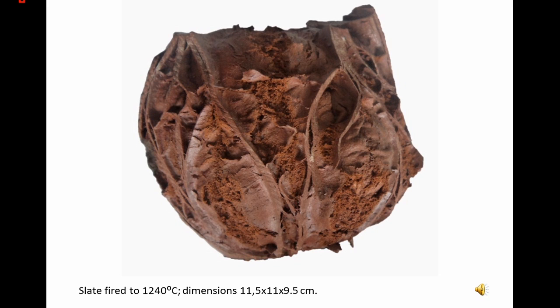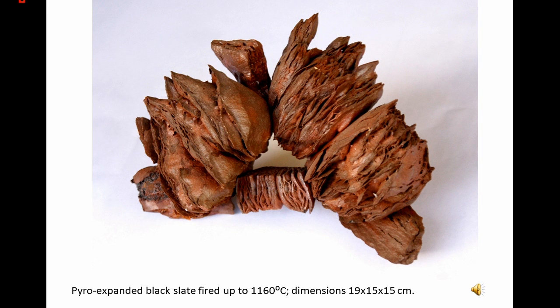Constrained pyroplastic expansion of slate. Expansion during the firing allows slate elements to interact between themselves in terms of a shaping process. This may happen in two different ways: assemblies and mortises. Assemblies are based on the fact that slate pieces stick together when in contact during the firing. They stick more strongly if the contact is strengthened by some kind of pressure, such as the weight of an